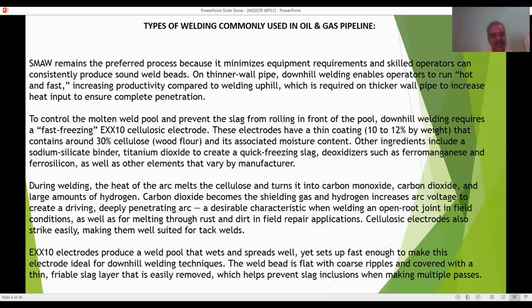Cellulose electrodes also strike easily, making them well suited for tack welds. E6010 electrode produces a weld pool that wets and spreads well. It sets up fast enough to make this electrode ideal for the downhill welding technique. The weld bead is flat with coarse ripples and covered with a thin friable slag layer that is easily removed, which helps to prevent slag inclusions when making multiple passes.